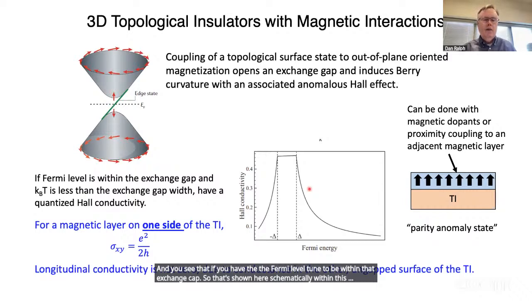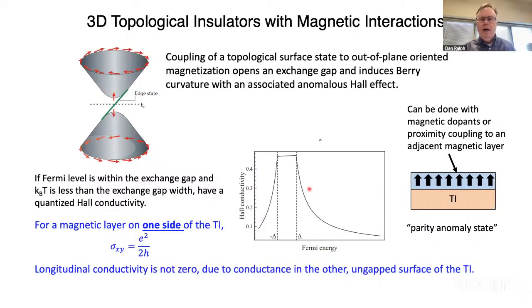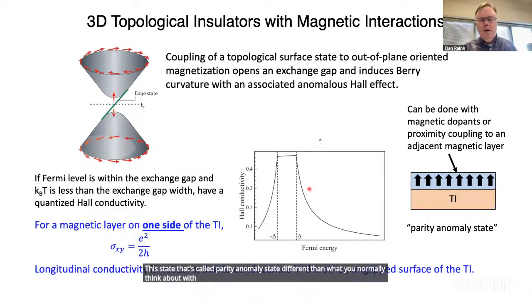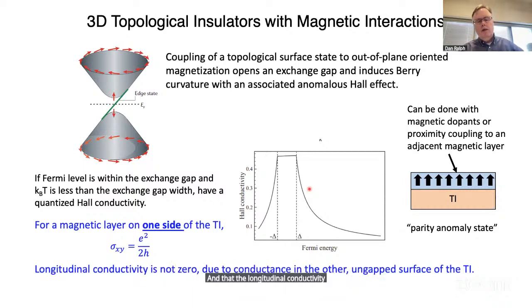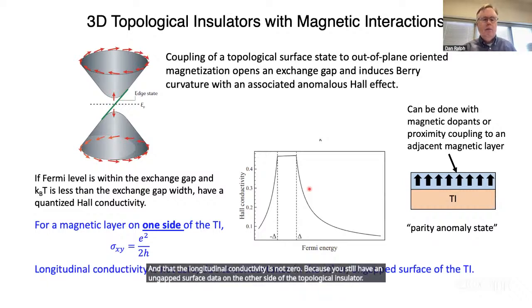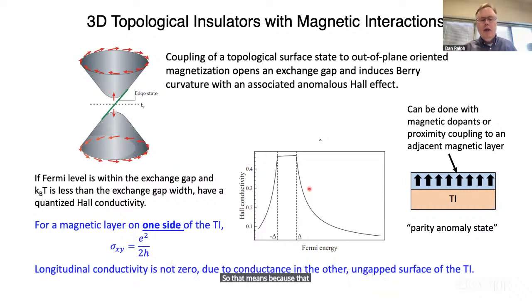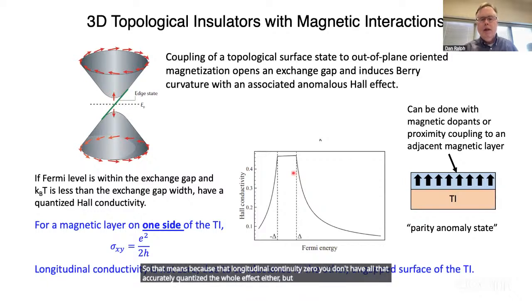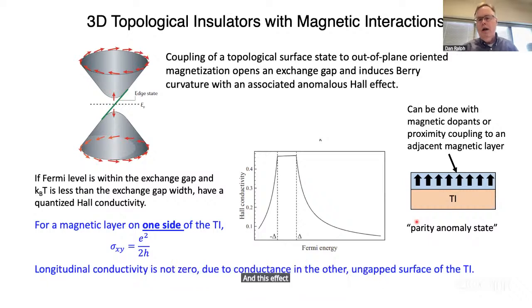This state, called the parity anomaly state, is different than what you normally think about with a quantized Hall effect in a large magnetic field, in that the longitudinal conductivity is not zero because you still have an ungapped surface state on the other side of the topological insulator. So that means you don't have all that accurately quantized a Hall effect either, but this kind of gives you the idea about what's going on. And this effect has been seen both with magnetic dopants and some of the other quantized Hall effect systems.